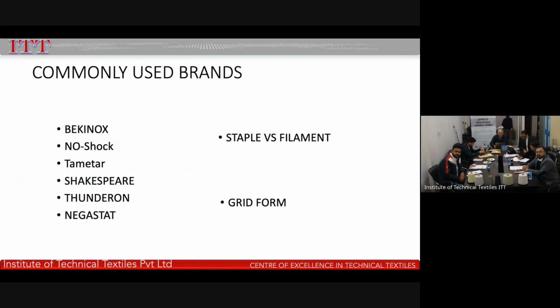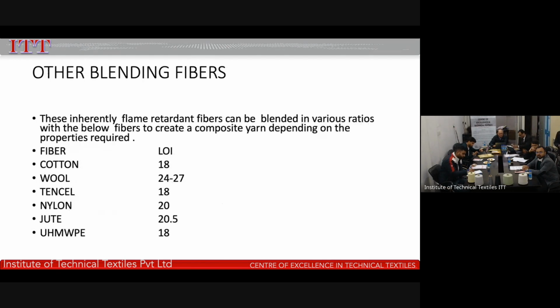The commonly used brands are Bekinox, No Shock, Tametar, Shakespeare, Thunderon, and Negastat. Now, this antistat is added to the fabric. Either it can be blended and then dispersed all over the fabric, or it can be in the grid form. This will depend upon the end applications. The other fibers that can be easily blended with these inherent fibers are cotton, which has, of course, a very low LOI of 18, wool, tencel, nylon, jute, and ultra high molecular weight polyethylene.